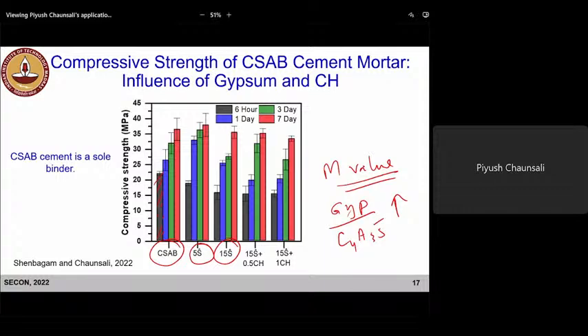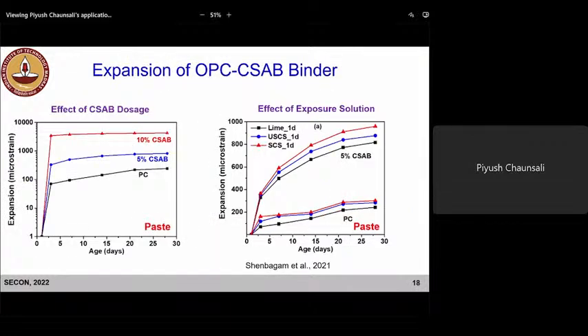Then we also looked at the effect of calcium hydroxide addition on top of gypsum. If we add some calcium hydroxide, how does the strength evolve? So in this case, again, CSAB cement is a sole binder, meaning no Portland cement was used. What we see here, I will first focus on the expansion. So this is Portland cement, right? If Portland cement is kept in a saturated environment, you see some small swelling, let's say 50 to 100 microstrain of expansion.